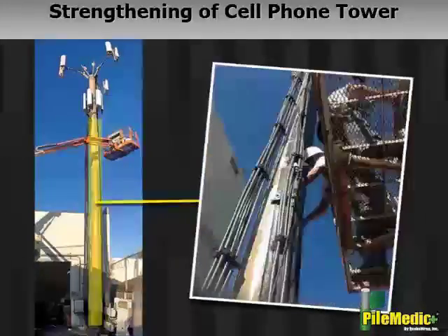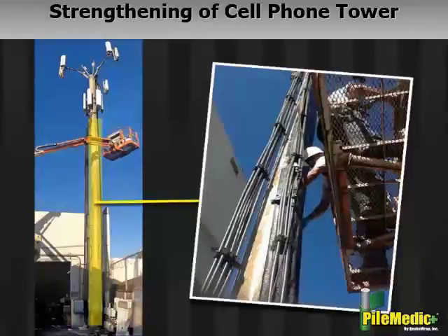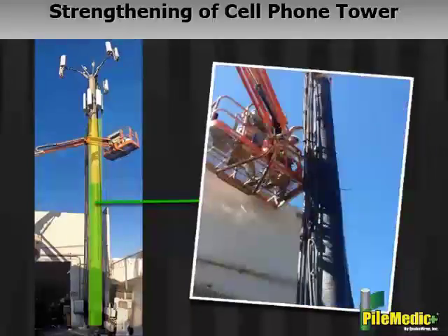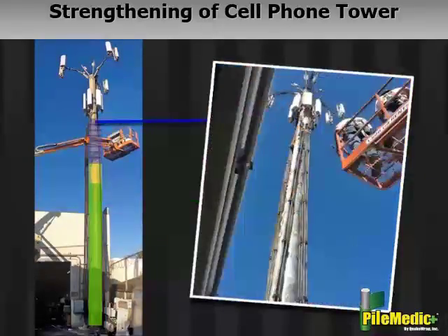2. One layer of QuakeWrap unidirectional carbon fabric saturated with QuakeBond epoxy was bonded in vertical bands to the entire height of the tower. 3. A second layer of the same carbon fabric was applied to the lower 2/3 of the tower height. 4. The entire height of the tower was then wrapped with resin-saturated glass fabric in horizontal bands.